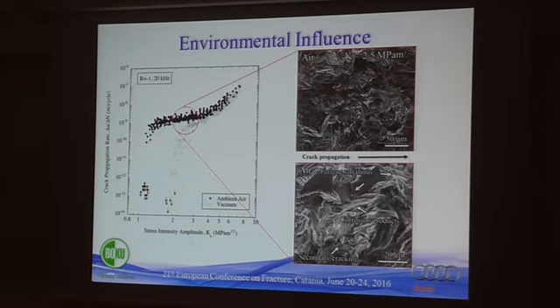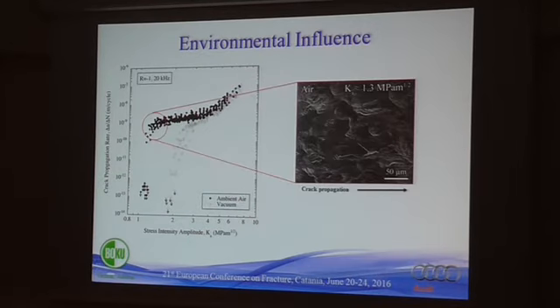And if we now take a closer look at the fracture surface obtained in that regime, we find more evidence for stress corrosion cracking. I already mentioned these cleavage facets, but also corrosion products and secondary cracking. And when we go further down into the threshold regime, we find that the fracture morphology in ambient air tends to smoothen again due to the increasing size of these cleavage facets.